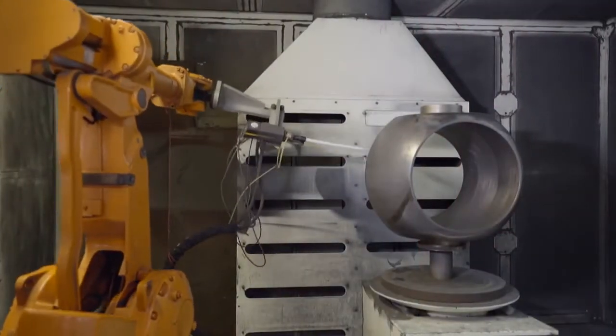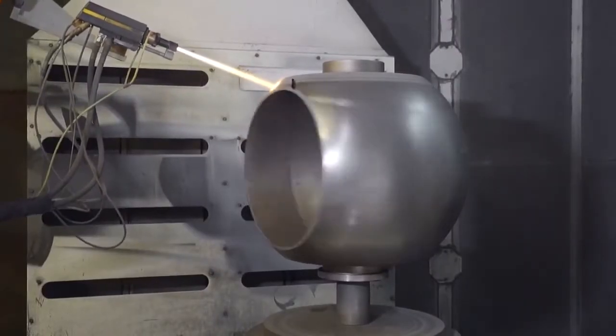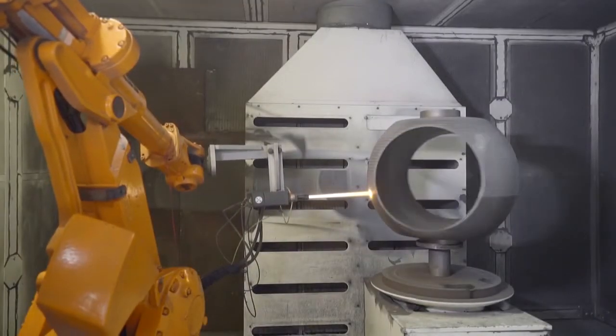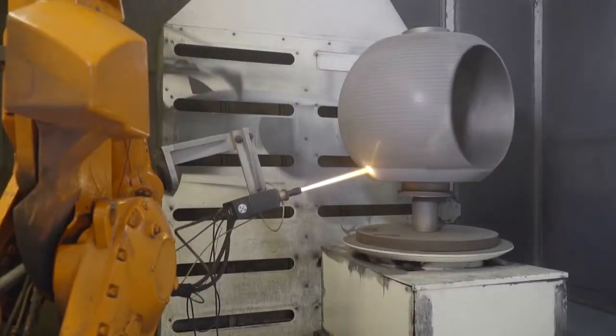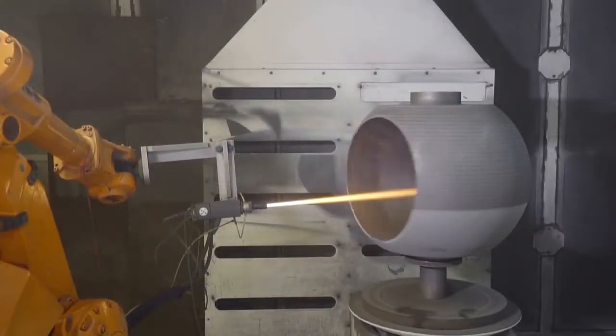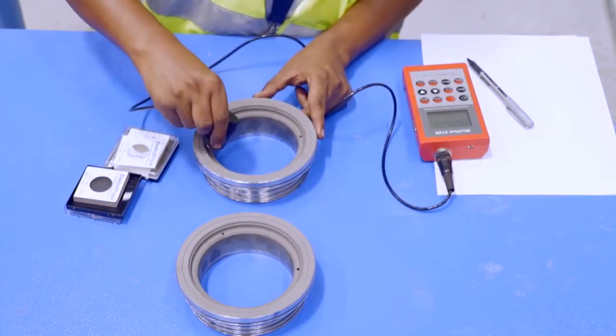The company has its own robotic HVOF coating facility. HVOF spraying improves corrosion and wear resistance, thus giving the valves a long working life. Depending on the design requirements, these machines at Camtec can provide thicknesses from 200 microns to several millimeters. Following the tungsten carbide and chromium carbide coating, all components are checked to ensure that the coating thickness conforms to the ITP, quality plan and other specifications.